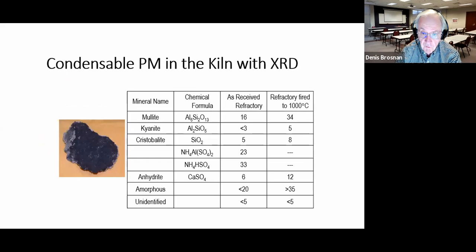In another instance, I was asked to look at condensable deposit on the exit end of the kiln near the stack that had accumulated in that kiln. And of course, being a ceramic engineer, the first thing I did is X-ray diffraction. What's in this thing? And so I found some components I expected, like mullite, perhaps kyanite, aluminosilicates, cristobalite, fairly high temperature kiln. But then I began to see some complex salts that I didn't expect. This was a solid piece that had to be chiseled off the wall of the kiln.